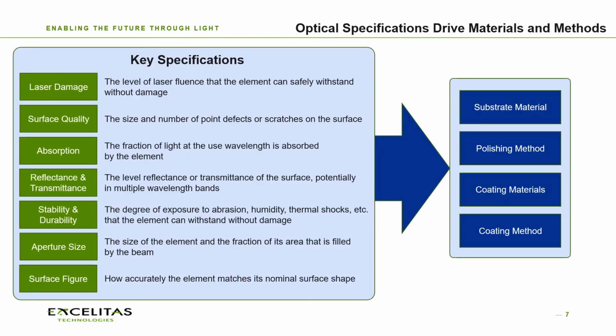Those four characteristics will typically be driven by seven specifications that we need to pay attention to when we're defining an optic for a laser system. The laser damage, how much fluence the optic can take before it's going to damage. The surface quality, what are the size and number of the defects, point defects and scratches. The absorption, how much of the light is going to get converted into heat. The reflectance and transmittance, how complex is that spectral band? How high a level of reflectivity are we going to have? The stability and durability, how dense and durable are the films or the optical materials? And then the size of the aperture, obviously a critical part of the specification, and then how precise the surface figure requirement is for any particular optic.